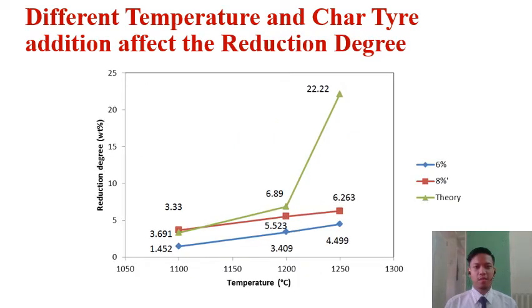This is the effect of different temperature and char tire addition on the reduction degree. And as you can see from the graph, at 6% char tire addition, the reduction degree at 1100 degrees Celsius is 1.452, and at 1200 degrees Celsius it reached 3.409, and lastly at 1250 degrees Celsius it reached 4.499.